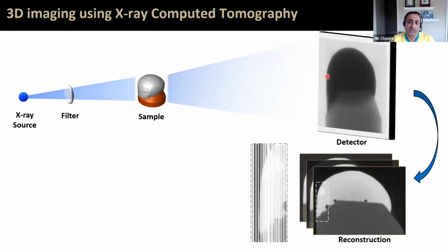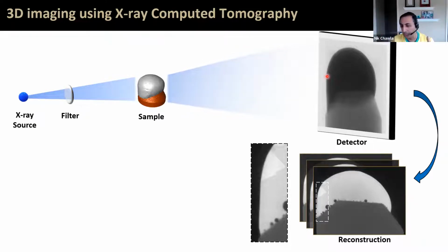And so we need to then do an inverse Fourier transform, what's called a filtered back projection algorithm, that takes those two-dimensional projections at different angles. We get a reconstruction in grayscale of our microstructure. And that particular data set at a given time can be resliced in any particular way and can be used for visualization purposes. You can take a video or something like that.